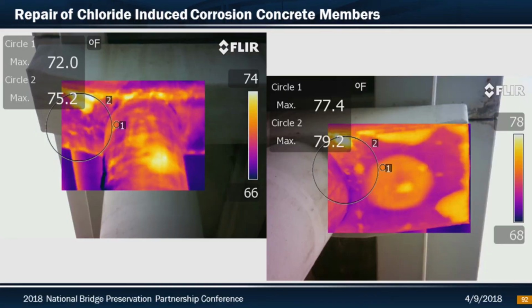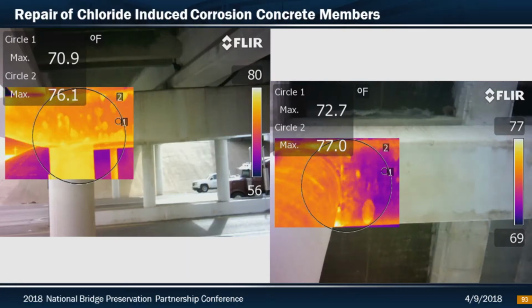We always want to know we have a good bond. Managed to get some actual photos with the FLIR showing what you would assume to be some delaminations between the FRP and the substrate under the soffits of the bent caps, edge of the columns. May be a potential for trapping water, chlorides, or contaminants. Again, would give some concern.